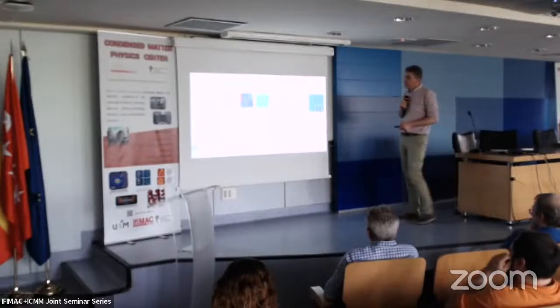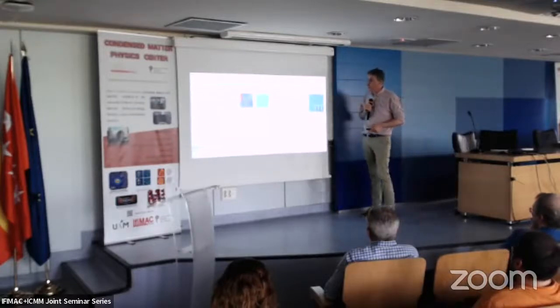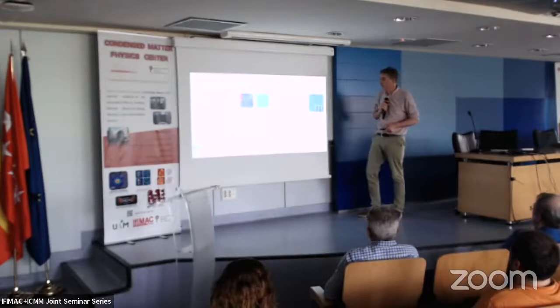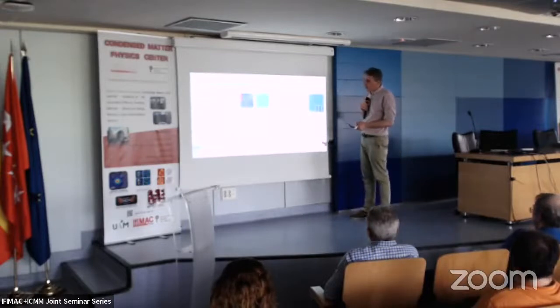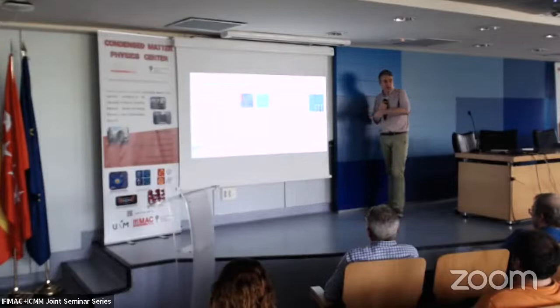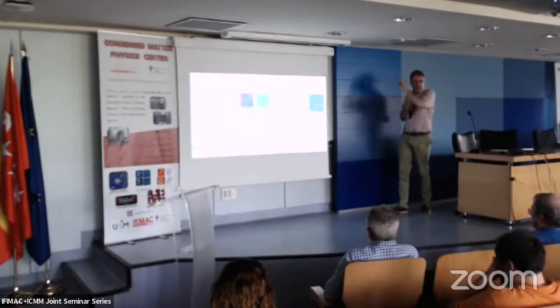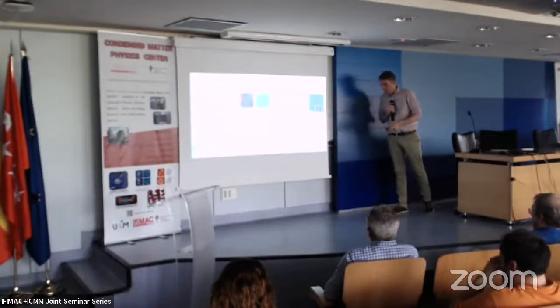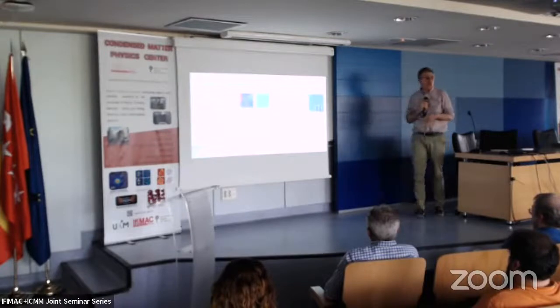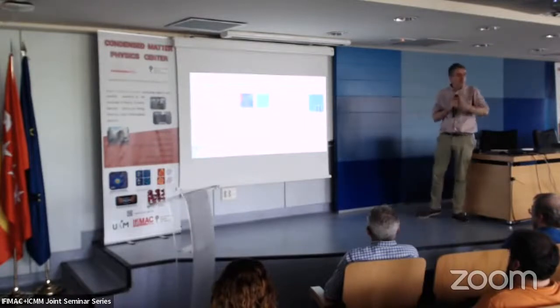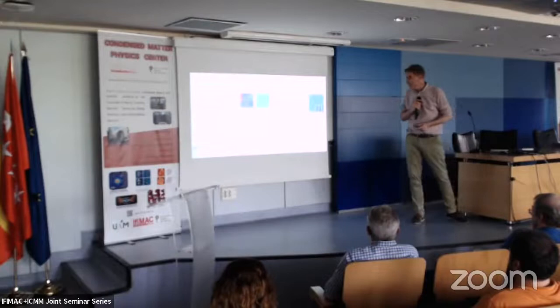And you see that these two systems here are superconducting, as well as URu2Si2. However, the signal which we see in the superconductor is extremely small. This is just a very small fraction of the whole density of states. So all these materials are triplet superconductors. So if there is a Majorana fermion, this material in particular is a triplet superconductor. This is a d-wave superconductor. But if there is a Majorana fermion, it will pop up at the surface of this system immediately.